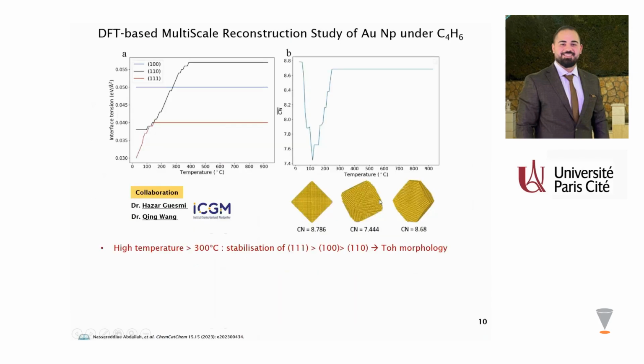To understand the interpretation and the observation obtained experimentally, a DFT-based multi-scale reconstruction study has been done on the gold nanoparticle and butadiene between room temperature and 900 degrees Celsius. First of all, the evolution of the calculated interface tension of the 111, 110, and 100 facets at high temperature shows stabilization of 111 and 100 facets more than 110 facets, which can explain the truncated octahedral morphology obtained experimentally at high temperature.